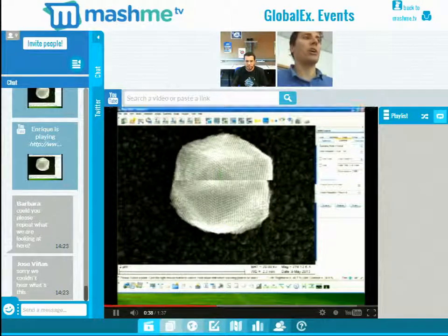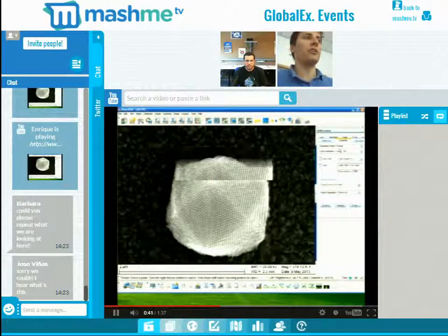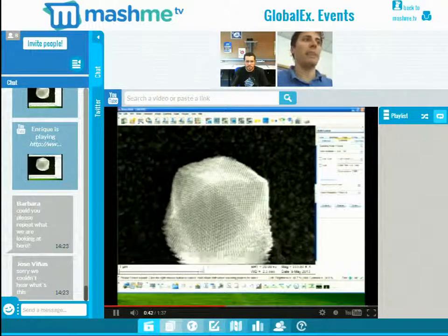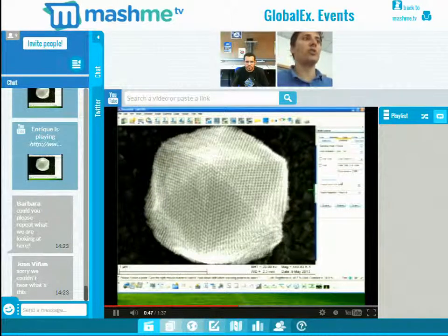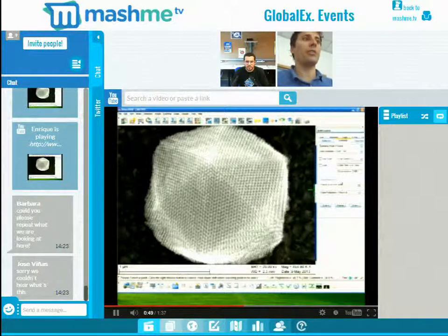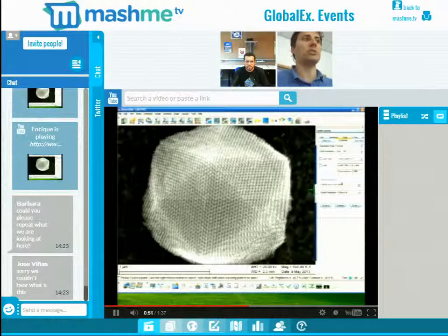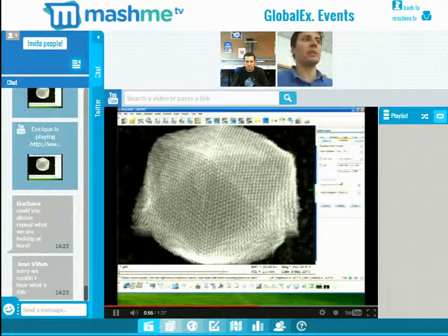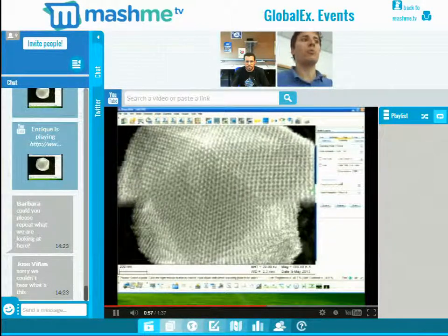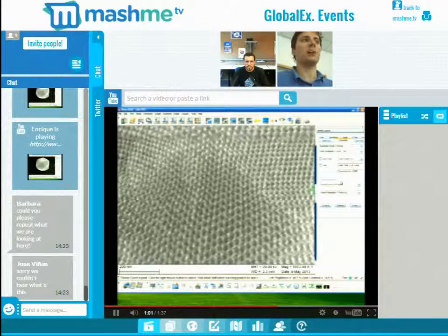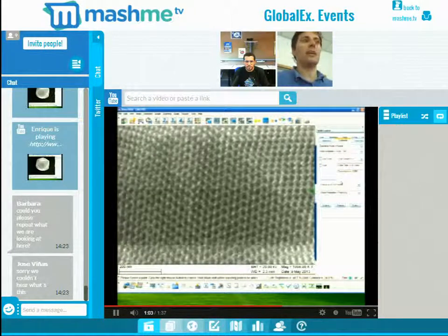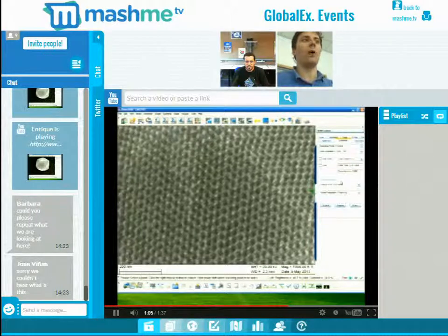Now, from here, zoom in further. As I said, it's made out of platinum. We used one of the polymer templates I showed you before to replicate them using electrochemical deposition. As you can see here, again, the struts are extremely small, and we use these materials for different applications, such as solar cells, batteries, catalysis, and sensors, because we have an extremely high surface area.